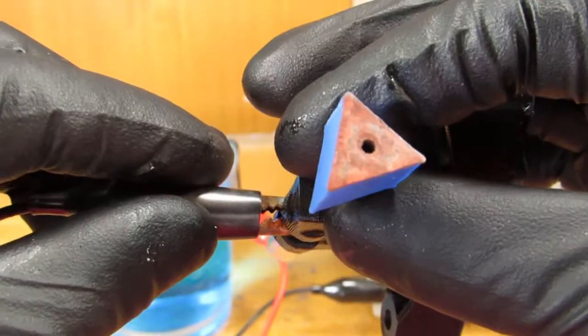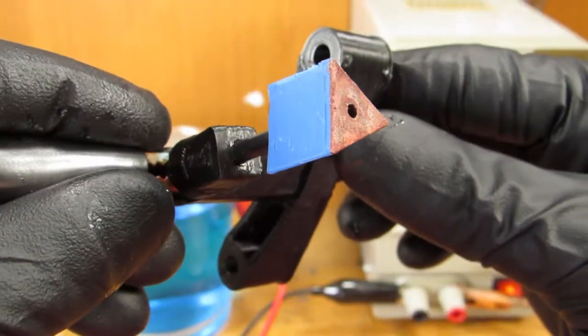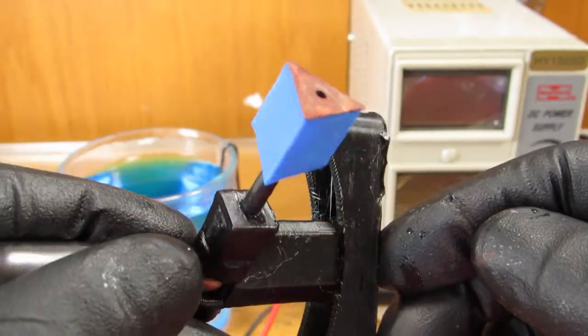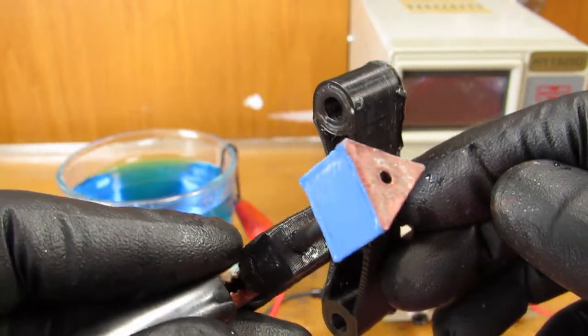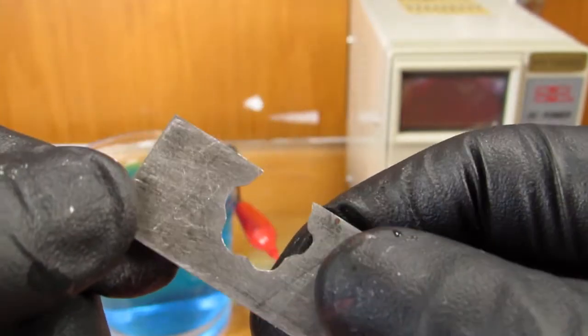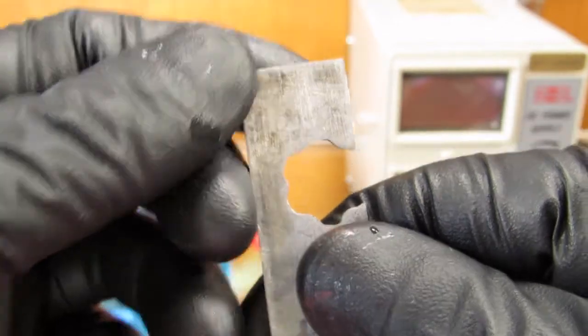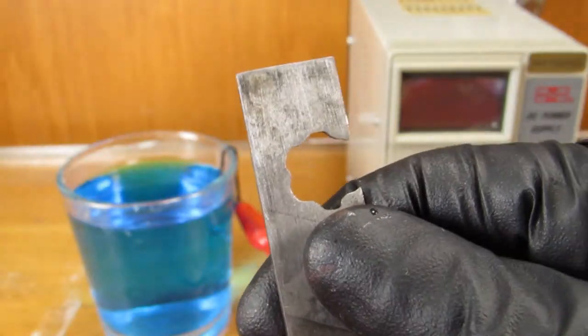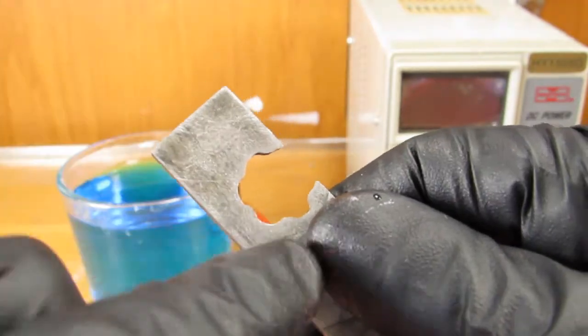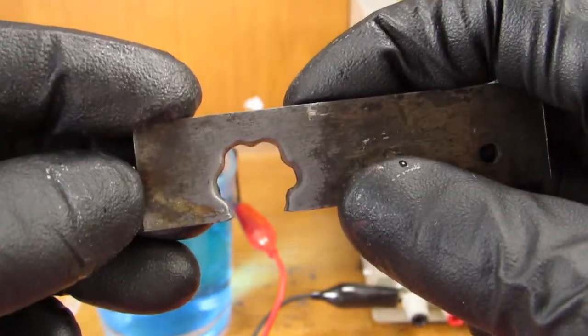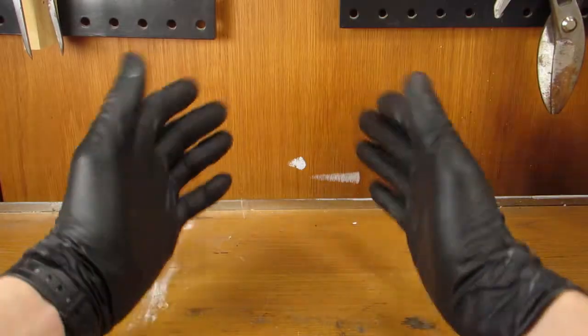I would let this plate for a few hours at least. Ideally you're going to have good chemistry with sulfuric acid as your acid in your bath there. That's going to give you a much stronger and brighter coating of copper, but still this process has been quite good enough for us to actually machine other things. Like I showed you earlier in the video, this was machined using the same method. Using a rounded profile might not be the best way to show the detail you can actually get out of this, but I still do think it's pretty impressive. Try machining this at home without using the electrochemical process. I don't know what type of machine you would use to machine hardened steel in such an odd shape, but I guess you'd use ours.